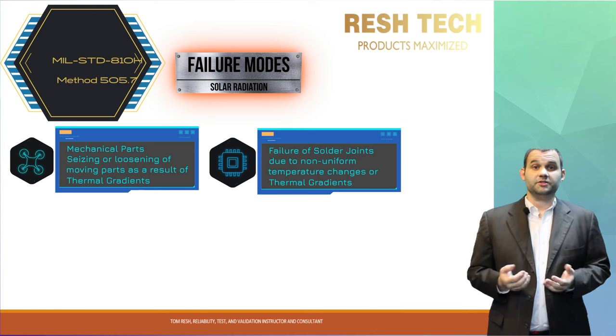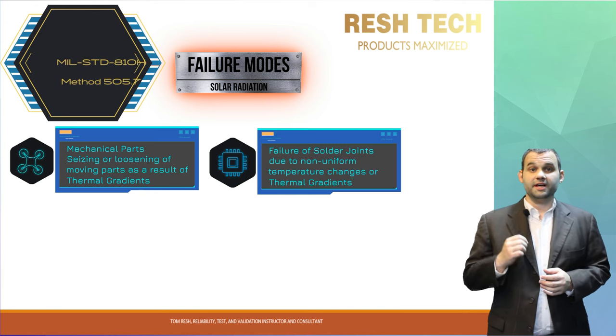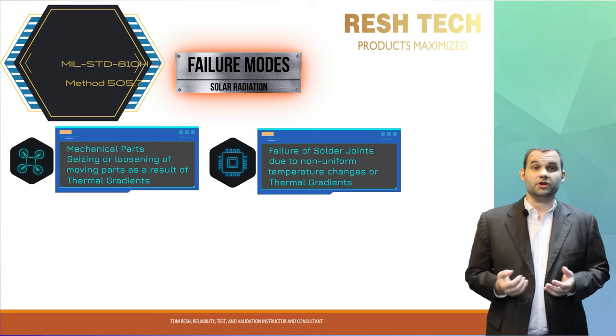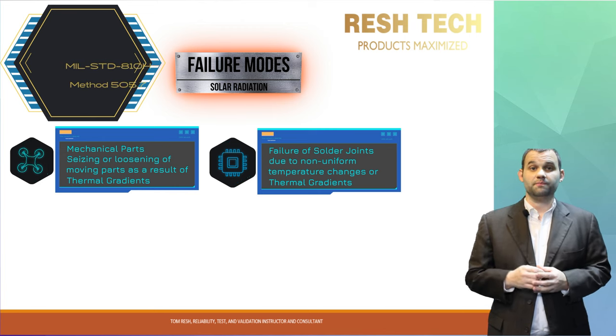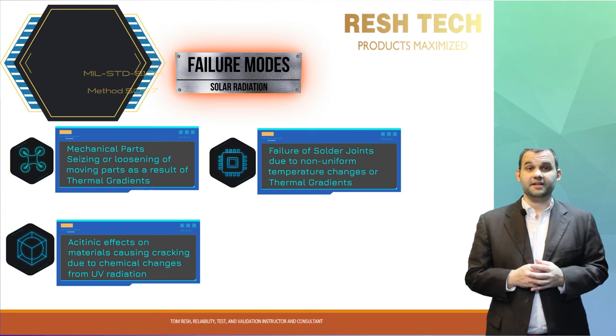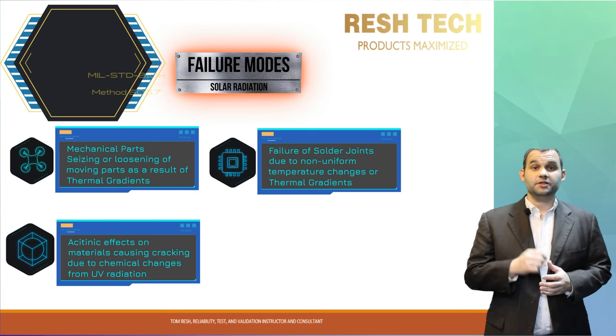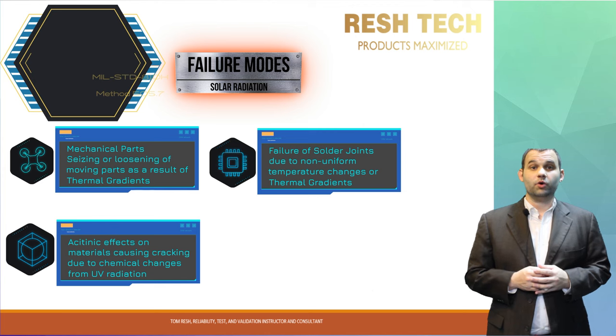Another failure mode is solder joints and adhesives, which can also become weak or break as a result of the non-uniform thermal exposure, and changes in strength and elasticity of materials as they change temperature at different rates. Also, fading and cracking of materials as a result of the actinic effects of ultraviolet light. This is where materials react or break down quickly when frequently exposed to ultraviolet light.